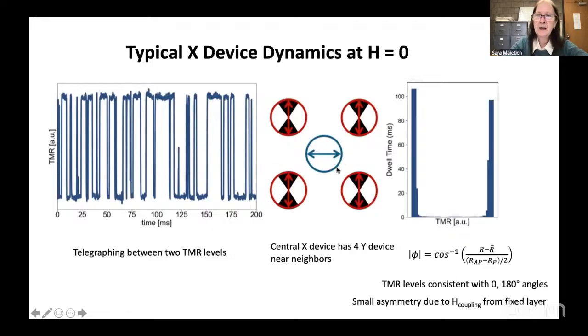So if we have an X device, it will have nearest neighbors that are all Y devices. So it should have magnetization that's jumping back and forth more or less perpendicular to it. And depending on the combination, they're going to give a net magnetostatic field at this X device. What we observe experimentally is that the X device resistance jumps between two different levels at zero field. So this is happening just from kT at room temperature. And if we decompose this into the angles that this central moment is spending time in, most of the time it's either at 0 degrees or 180 degrees. So that makes sense. There's a little asymmetry because the fixed layer has a small fringe field that we haven't canceled, but that's about 8 Oersted, very small.